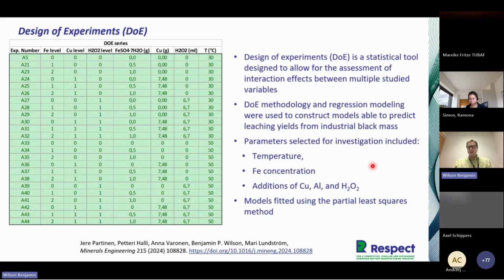So the parameters we selected for this investigation included temperature, the concentration of the iron, not just what was already in the black mass, but what we added in terms of the iron sulfide and sulfate, and also the additions of copper and aluminium or peroxide. And then the models were fitted with a partial least squares model. And you can design the experimental protocol. There are programs to help you design this, so you can have different experiments with different levels of iron or copper and peroxide, and this provides you the information to base your statistical model on afterwards.